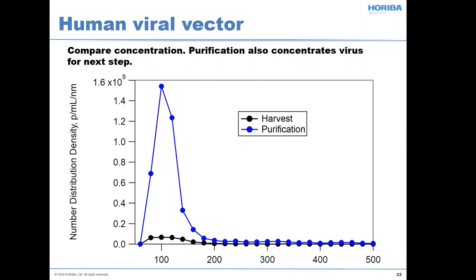The next part of the story: plotting concentration in actual concentration units — particles per ml per nanometer — shows that the purification significantly increased the particle concentration as well as narrowing the particle size distribution. On the larger particle size end, it almost looks like a dewatering step, though obviously it's not. What you can say is: I took away a whole bunch of dispersion, and that purification did two jobs. This really points to how multi-laser nanoparticle tracking analysis can help you keep score in your virus manufacturing.